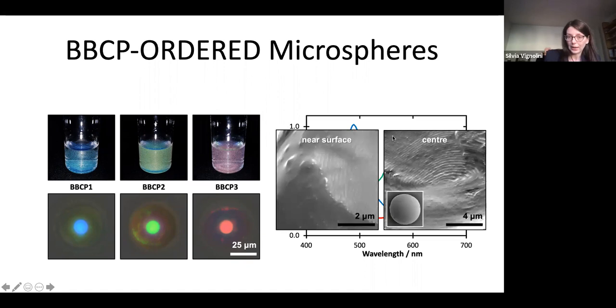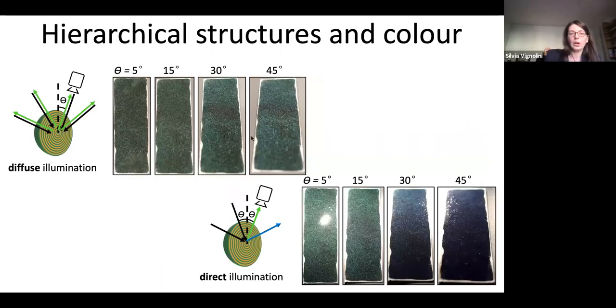And as you can see here, when you look at the inside of the spheres, you can again recognize this layered structure, and it is more or less on the same scale as what I was showing you before with the cellulose, in such a way that you can produce this coloration. What is cool is that, as I was telling you before, since the spheres are a little bit larger, this effect of hierarchical structure, because they are so ordered, so perfect, you still maintain some angular-dependent optical response when you look at them in direct illumination. Instead, in diffuse illumination, the color is again constant independent of the angle of observation.